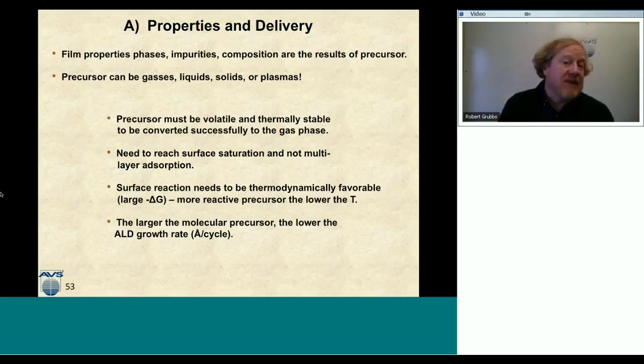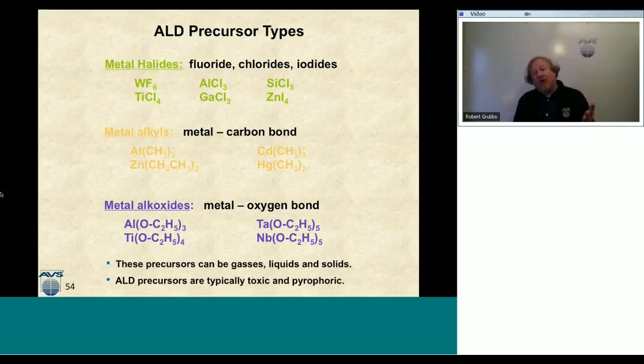So let's take a look at some typical precursors. We have 4 classes of precursors. We can have metal halides, we can have metal alkyls, metal alkoxides, and we can have organometallic compounds. So metal halides, I talked about the tungsten hexafluoride that we use for tungsten ALD. We have titanium tetrachloride that we can use for titanium oxide. We have aluminum trichloride. Aluminum trichloride is actually a solid. And we also have other iodides and chlorides and bromides. So this is sort of like the metal halide camp of ALD precursors.